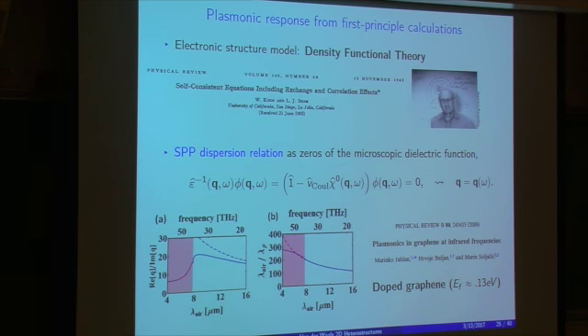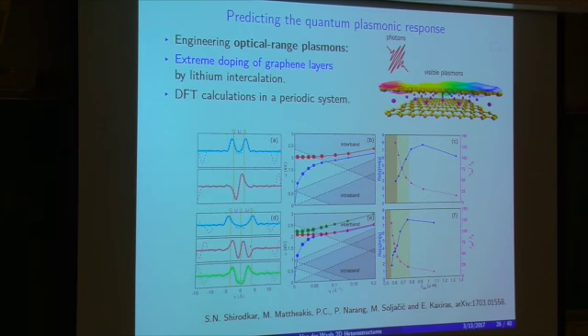So this has been done, for example, for graphene over here. So we know that in a frequency range, which is a terahertz, so below infrared, we will have a plasmonic response, which is damped if we look at too high frequencies. And what is interesting is to look at the ratio of the wavelength in the air and the wavelength in the material itself. And we see that this ratio is about 100 to 200. So we have a factor of 2 orders of magnitude between the wavelength in the free air and the wavelength of the plasmon. This is what plasmons are all about. Now, what we have been working a little bit on is how to engineer plasmons that have even higher frequency, so optical range in particular.